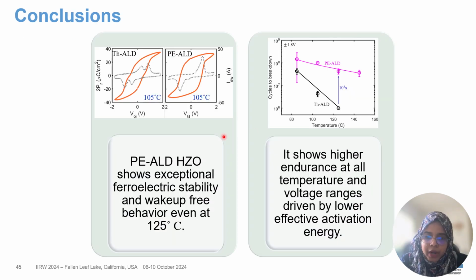So if I have to summarize my whole talk, what I have been talking about is how we can improve the wake-up effect and also the endurance of our ferroelectric capacitors. Here we have used one simple solution. We have just replaced the thermal ALD deposition process of the ferroelectric film with plasma enhanced ALD. And what we are seeing is that we don't need any wake-up cycles to wake it up. It is a wake-up free device, and also we are getting better endurance for a wide range of temperature from room to elevated levels.